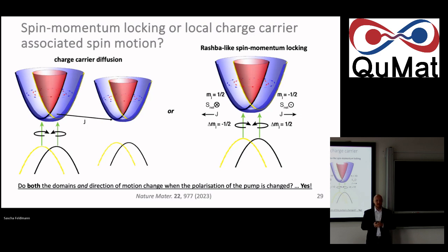Now, there's one easy way to check whether we are crazy or whether it's much more mundane than that. And that is to say, let's just switch the initial spin. So I just use my other handedness of circular polarized pump. So I don't initiate spin up, but spin down. And if it doesn't care about the spin, it will still flow just downhill in energy one way anyways. But if it does care, it now flows the other way. We didn't change anything else about the energy landscape. We just would change the spin.